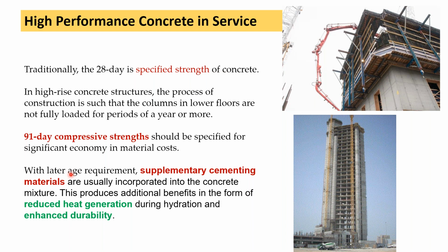Now, this becomes a problem if I'm going to start using lower reactive supplementary cementitious materials as clinker substitutes. And the other thing is, when we have structures like a high-rise building, achieving fast strength is really not required, because even with a 7-day slab cycle, the columns on the lower floors will not see loading until much later than a few months. And so the requirement for this 28-day strength is misplaced. And perhaps a 90-day compressive strength may be a better indicator of strength as it is applicable for use with supplementary cementitious material. And I think this is one of those things that we have to look at more carefully if we are going to promote the use of more blended cements.